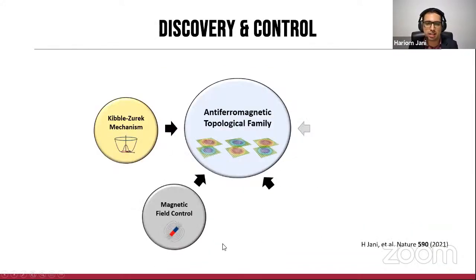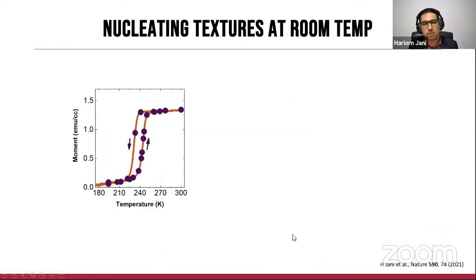Now, having looked at that, let's look at another control mechanism, which is chemical control. The first set of images that I showed you actually had the transition sitting at 240 Kelvin. While this is good proof of principle, if you want to do realistic use of these textures, it has to be sitting at room temperature or above. And therefore, we investigated how this can be done.